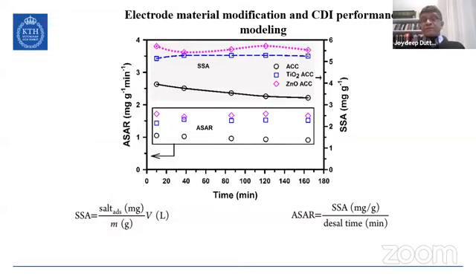Of course, modeling goes hand in hand with the experiments. And we have been looking at what we have termed as SAR, or specific salt adsorption ratio. And we were checking how we stand. It seems that zinc oxide ACC is quite similar to the titania coatings, but it's much better than just having simple electrodes made of activated carbon.